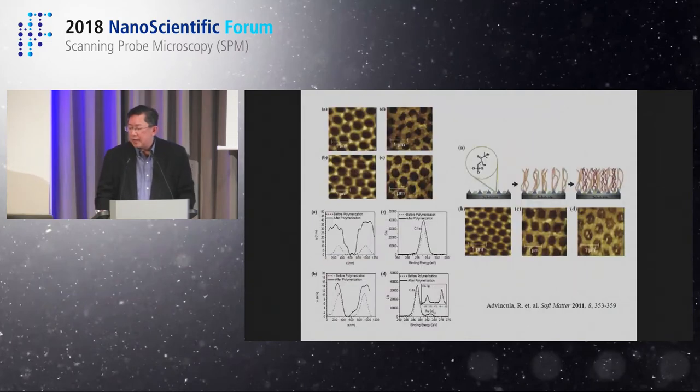And we've since done that on those two other types of samples. Since the middle part is accessible for grafting another polymer, we then grafted an ATRP initiator and then grew a polymer brush. So this is a way of having a ternary composition, two polymer brushes and a conducting polymer, on a single, highly patterned surface.